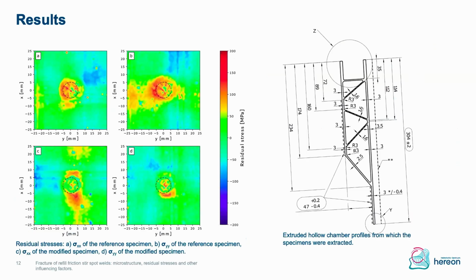Additionally, we did some residual stress measurements with X-ray diffraction in transmission. First of all, I want to say we have some residual stress profiles, which you see here. They come from the extruded hollow chamber profile where we took the samples from, but basically should not influence the fatigue properties, since the residual stresses are formed by the welding process anyway. Again, on top we have the reference specimen where you see the typical residual stress distribution, having a huge amount of tensile residual stresses within the spot weld and around it.